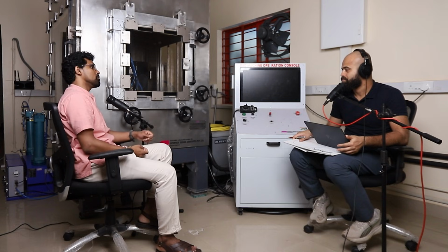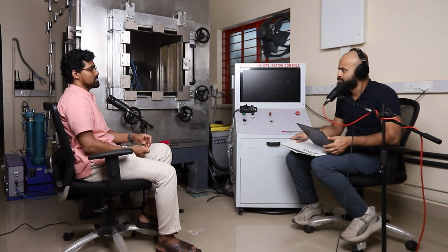Because we were already trying to grow a single crystal using that setup, we were growing some small rods. So we thought, okay, why not build a single crystal using additive manufacturing? That's how we got into this, and whatever understanding we have developed. You're asking what kind of single crystal parts we have been able to make using 3D printing. We were able to make, and understand the physics of growing, single track walls as well as 10 mm diameter rods. We have been able to build a 10 mm diameter rod of height 100 mm, one single grain.